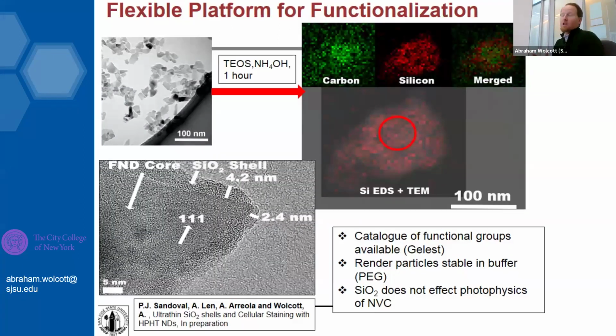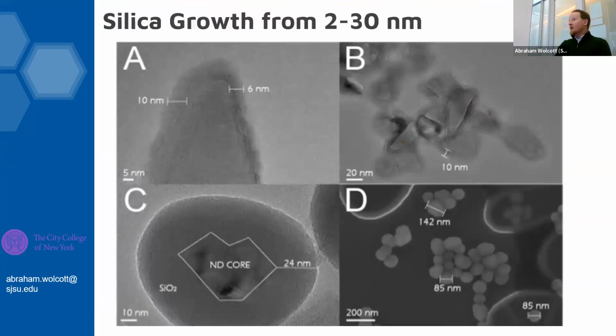What isn't suspicious is that we can use electron microscopy to validate that we have SiO2 on the surface. This is before, this is after the growth. We can verify it is on these edges of our HPHT diamond. You can get it down to 2 nanometers or less, and you have this jagged looking material with a light coating occurring there. But it's quite versatile, and people for many, many years have used silica chemistry on a number of nanomaterials, including quantum dots, gold, silver nanoparticles, and the like.